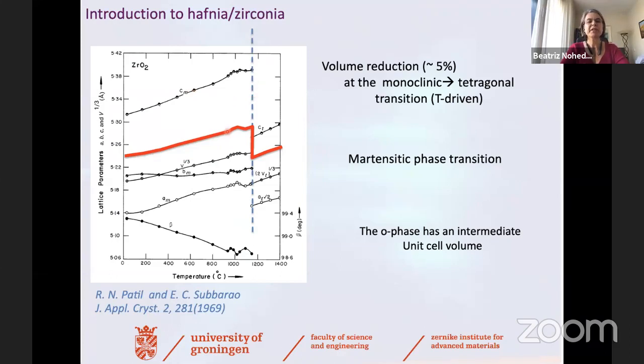At some point, it was all a little bit confusing at the beginning. But more and more things were being learned about the material. For example, it was known that zirconia and hafnia have a martensitic phase transition at high temperatures that involves a huge reduction in volume. So the ground state monoclinic phase has a larger volume than the high temperature tetragonal phase above the martensitic transition. And it happened that this orthorhombic phase that was stabilized in these very thin films seemed to be an intermediate phase between the tetragonal and the monoclinic phase.